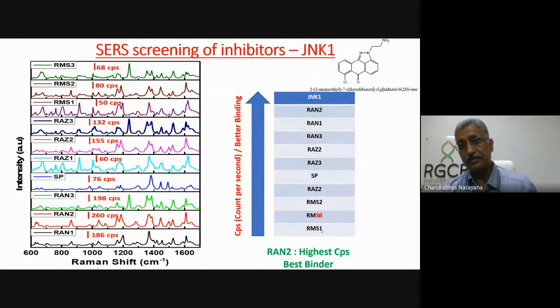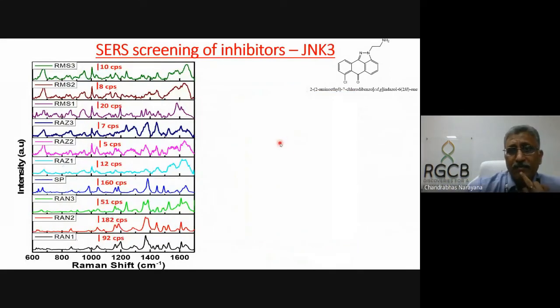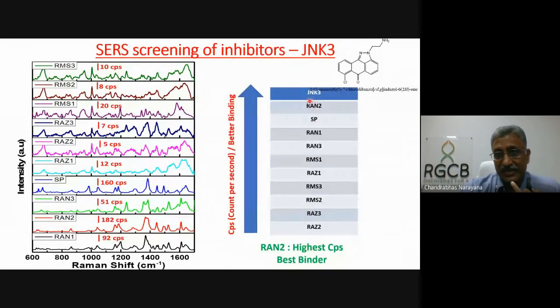In fact, we checked this with the biochemical assays, and we found a one-to-one correspondence. Now, when we put it in JNK3, even here RAN2 binds much better compared to the SP, but it is not very different. You can see RAN2 is 182 here, and SP is 160, so it is more or less similar. You can rank it, and this ranking exactly matches the biochemistry of the system. So by just looking at this Raman, you can immediately know which molecules you need to work with, because all the molecules that work better than the original molecule are the ones you need to work on. Hence we have localized that RAN2 is the better molecule to work with.